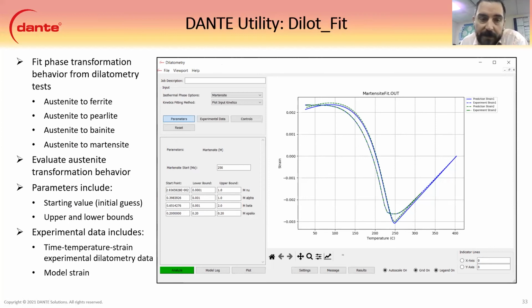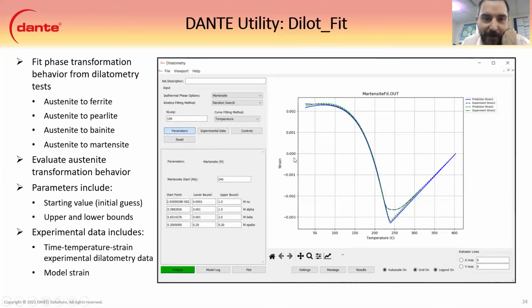You can get this through experimental dilatometry data, and then you can fit the data with this utility to the DANTE material database or the user database and create your own material based on these. And you can see here I have a little bit of an animation transition between the two. This fit wasn't exactly to our liking, especially on the lower temperature end. So we ran a loop with 100 iterations to try to fit it a little better and increase the martensite temperature, and the magic works. And we get a much better fit based on that.